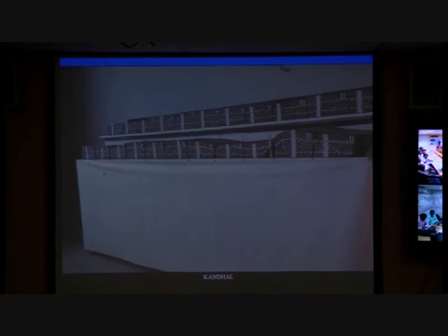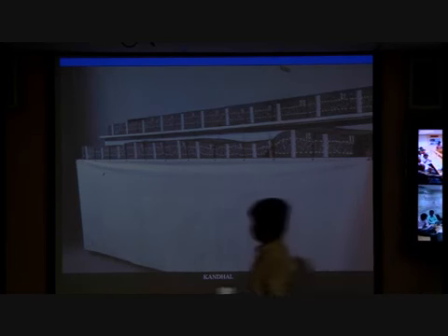At the bottom, you see the one which was rutting. On the top, there was hardly any traffic. So in the bottom, we joined all these blocks in that one lane, and you can see the rutting in the wheel track area. It shows all the 3 layers. We put some white paint and demarcated them. So you can see here in the bottom assembly of these blocks the wheel track rutting, and here there is heave. So you can see here that the rutting is taking place in the binder course. Here the thickness of the binder course DBM grading 2 is less in the wheel track and more at the edge of the wheel track, and the BC is just simply riding on it.